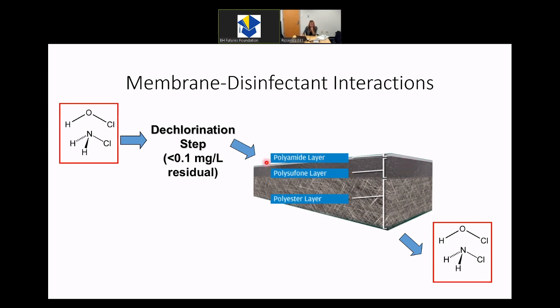And it's important to make sure that the chlorine is dechlorinated, or there is a step to make sure that the residual is less than 0.1 milligrams per liter, so that there is not damage to the chemical structure that is the polyamide layer. So after the water passes through the membrane, then you will likely have another chlorination event for the residual.